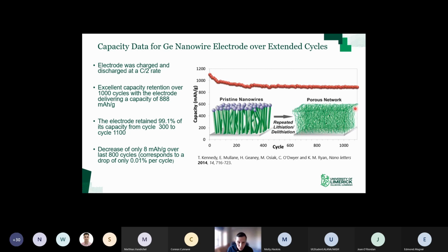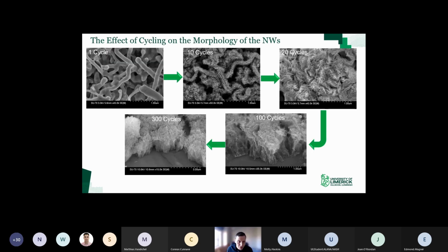What we saw was this porous network of ligaments, basically, of the active material, germanium. So we investigated that further, and we did staged cycling of these. We looked at the material after 1, 10, 20, 100 and 300 cycles. And what we saw then was the progressive deforming of the morphology. So after 1 cycle, you still had nanowires. After 10, you could see the surface had become much rougher. After 20, it was much more difficult to even make out the individual nanowires.